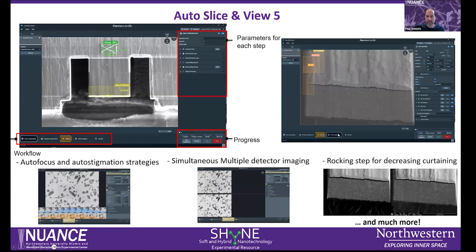On the right-hand side is the SEM imaging tab, which shows an electron beam image. This area is about 75 microns wide, so it's a relatively large cross-section. There, again, you have a multitude of parameters you can set, like different autofocus or auto-stigmation strategies, whether you do fast focus or slow focus. You can use multiple detectors simultaneously, like the TLD and the ICD detector, for backscatter comparison.